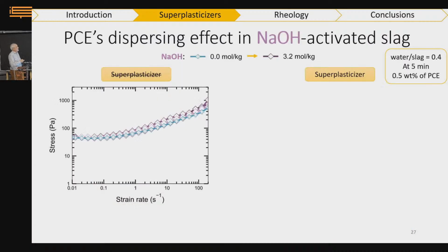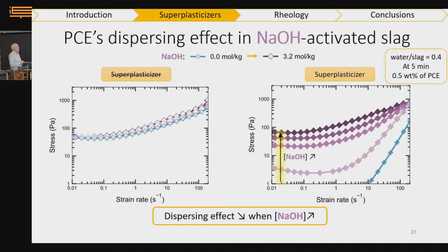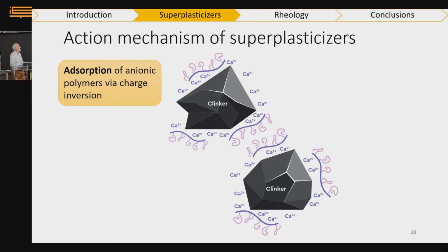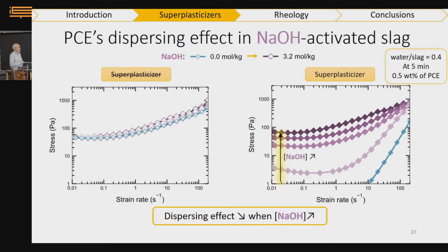Again, with no superplasticizers, activation at very early time doesn't change the yield stress of the system, taken as the minimum of this curve here. But what's interesting is that when I add the superplasticizer, do you remember without activation it worked very well? The yield stress was drastically depressed by orders of magnitude. And as I gradually increase the concentration of sodium hydroxide, going up to 3 moles per kilogram, but those are intermediate values, you see that the yield stress comes back progressively. So we are not dealing with a phase transition here. It's more complex than that. But clearly, the presence of the sodium hydroxide modifies the behavior of the polymer. So let's focus first on the sodium hydroxide, because this is where everything is simplest, I think.